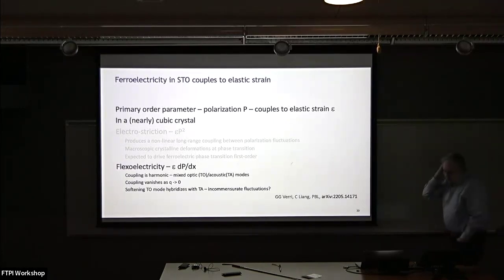So actually, what I want to talk about, for the purposes of this talk, is coupling to elastic strain. And there are two natural forms of that. If I've got an order parameter, a vector of polarization P, and a material which is cubic, and it isn't quite cubic, but I'll pretend it is, you would have a coupling where the elastic strain will couple with the square of the polarization. So a non-linear term. That's called electrostriction, and that does interesting things, which I'm not going to talk about.